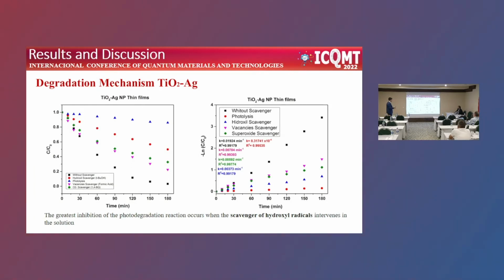So how can I explain what is happening for this type of material? Because you are using these two materials, in this case the titanium oxide too, but the difference with the silver nanoparticle is really high. Well, we put different scavengers in order to explain the mechanism for this type of photocatalysis. So we put a hydroxyl scavenger, a vacancy scavenger, and a superoxide scavenger in order to try to understand which species can degrade the pollutant.